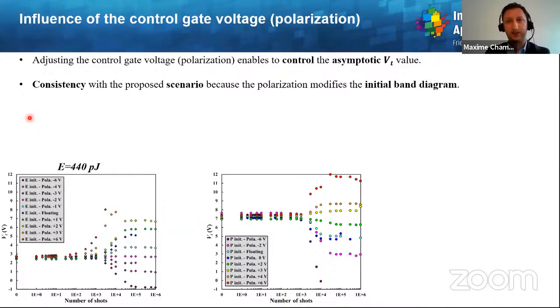So in order to test this theoretical scenario, we have carried out two experiments. The first experiment consists in using a control gate voltage, which is called polarization or bias. And here you can see the threshold voltage as a function of the number of shots for initially erased and programmed flash memories. One can see that by having different bias, you can play on the final state of your laser-induced programming, which means that adjusting the polarization enables us to control the asymptotic VT value.